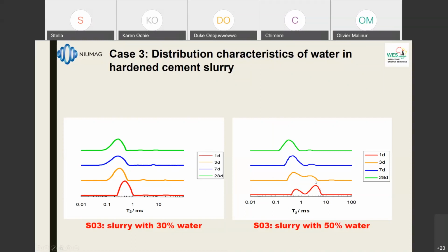And the more we wait, the more this free water will disappear, the 50%, until after 28 days, we still have a little bit of free water there, but we can see that the time is between, let's say, 0.1 milliseconds and 1 millisecond. And here we see the time is also 0.1 to a little bit less than 1 millisecond. So we got almost the same spectrum after 28 days, but it took longer to dry, which we understood with 50% water. But we can make experiments like this, quite interesting for cement. Look at the curing time of cement. Look at the optimal percentage of water, etc.